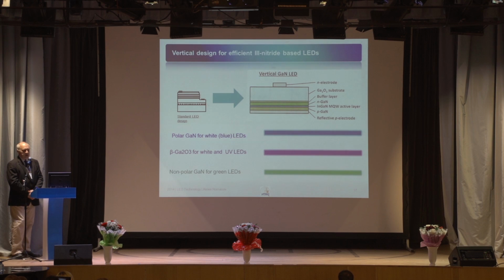The other possibility is to change the construction of the light emitting chip. Here is shown the traditional so-called standard horizontal LED structure, when the current goes horizontally through the chip and different elements are demonstrated. It is proposed to change the structure to the vertical geometry, where the current can go from the top to the bottom. And in this case, the current will spread rather uniformly, and the working zone of the device where this heterostructure is sitting will therefore be loaded more uniformly.